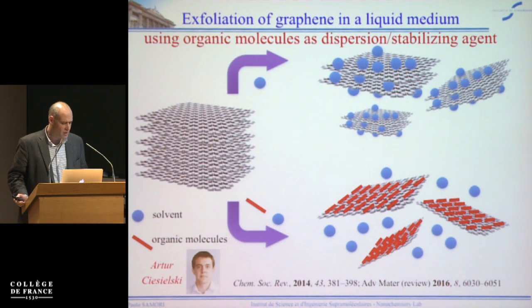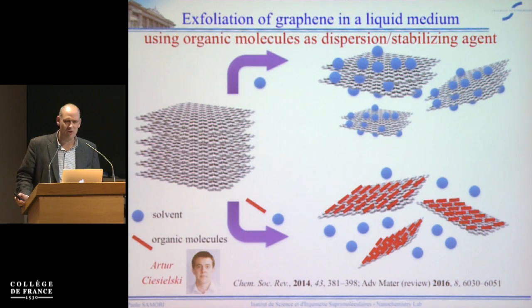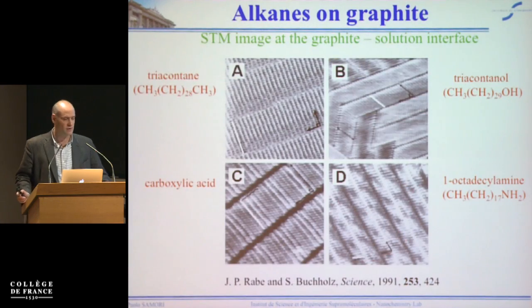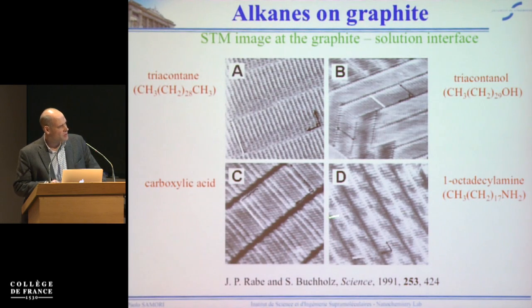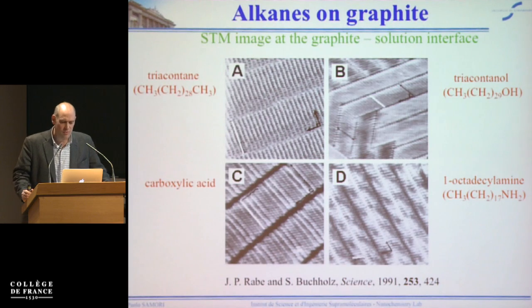Usually in the community, this kind of approach has been pioneered by Johnny Coleman and Andrea Ferrari, who are physicists, and so they are less creative, or let's say more narrow in their choice of chemical system. The chemical system we decided to play with is very banal, so purely alkanes. And the reason why I chose alkanes was because I was thinking about the work that my PhD advisor, Jürgen Rabe, published in 1991. This was the first work on solid-liquid interface study by scanning tunneling microscopy of alkanes on graphite. And it showed that whatever end group the linear alkane can have, like methyl, carboxylic, amino, or OH group, they form lamellae.